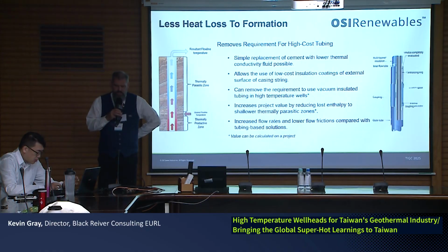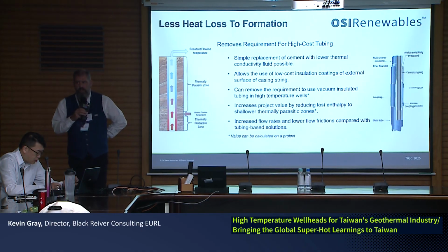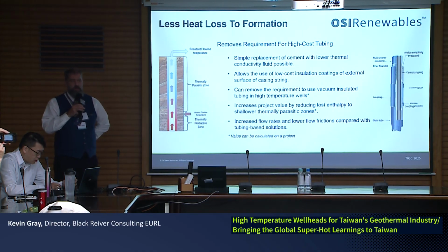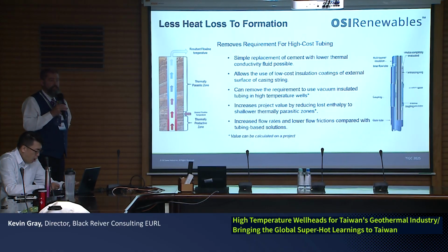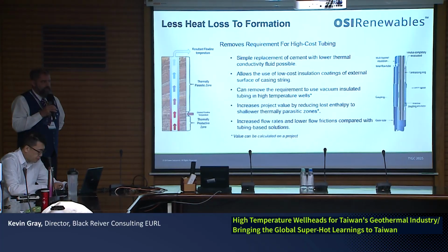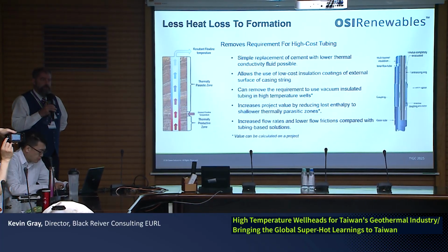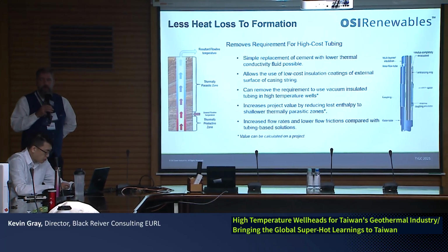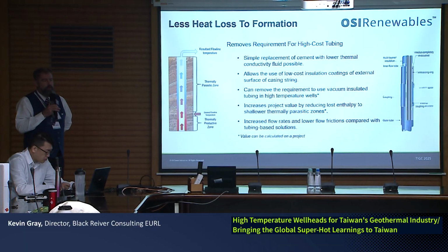The other issue is that cement is actually a relatively good conductor. Although we can go to a foaming cement, we can go to a cement with a lower thermal conductivity. Typically, cement is going to conduct the heat from our well much more efficiently than leaving a fluid in the annulus, or even better, a very simple external foam-based insulation sprayed on our casing.